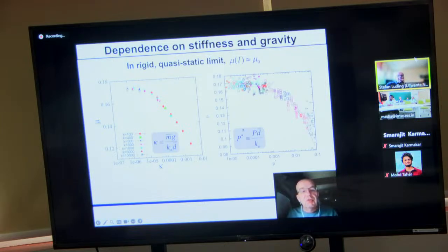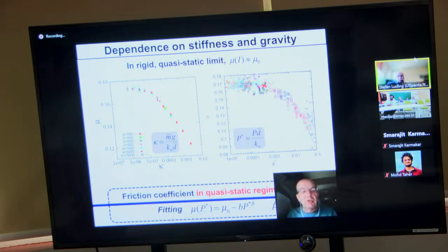Now, what happens if I do not only change the shear rate, but I also change the stiffness or gravity? It gives me no data collapse to begin with, but if I find the right dimensionless combination, then the data actually do collapse. I can also rewrite this a bit, express it as dimensionless stress, and then the collapsed data for many different simulations follow also a trend, and the friction is actually going down. The bulk friction is going down with the non-dimensional stress. They are collapsing, but the trend is qualitatively different. This looks like a constant minus a function of dimensionless pressure to the power beta. And here beta is 0.5.